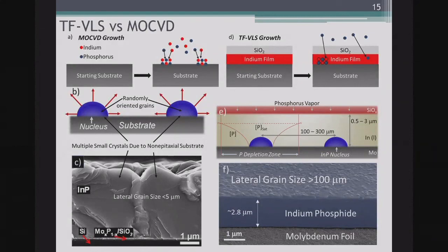Okay. So there's a lot of details in the material science behind how that works, but fundamentally, the reason it works is that when you use a vapor phase process, we get a whole bunch of little nuclei of our crystals, and those nuclei will grow out and touch each other, and there's no relationship between them, so as soon as they touch, that's a boundary, a defect. On our side, we actually control it, so I only create one nucleus, and then I just grow that nucleus out.